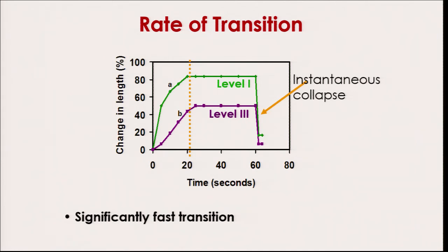That means almost 80% of the change occurs within 20 seconds as it swells. And if I change from the lower temperature to the higher temperature, the change is almost spontaneous, instantaneous. The fiber will collapse immediately within a fraction of a second. So, this shows that the transition is significantly fast.